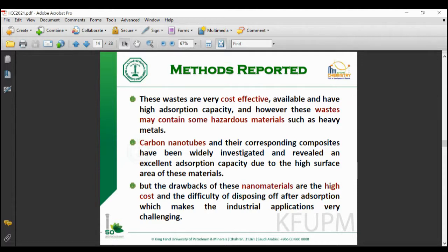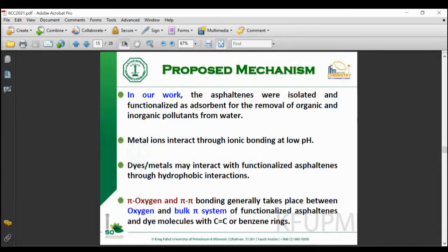Carbon nanotubes are very effective, but at the same time they are costly. When we talk about carbon nanotubes, carbon nanofibers, or carbon nanomaterials, they are costly, and there are still no clear protocols available for safety: how we are going to take care of safety if anything happens with these nanomaterials overall. So ultimately, in our work, we took the asphaltenes, isolated them from the high boiling fractions of the crude oil, and then tried to functionalize and oxidize them. As I said, initially I failed, but then we used a mixture of acids, and it gave us good results. First we characterized it, and after that it bore oxygen, and that helps to adsorb the metals, the dyes, and others.